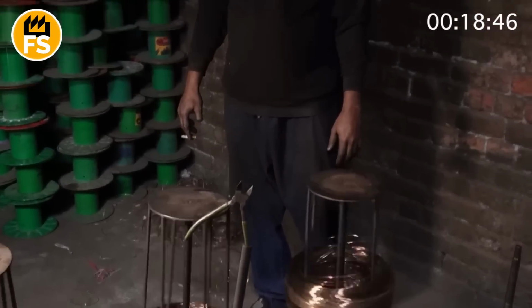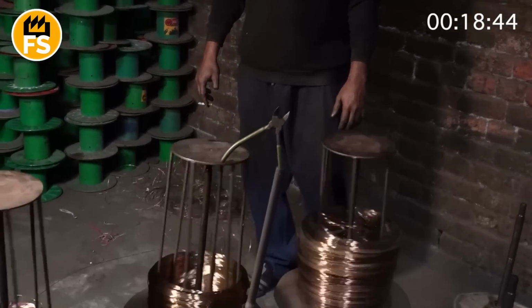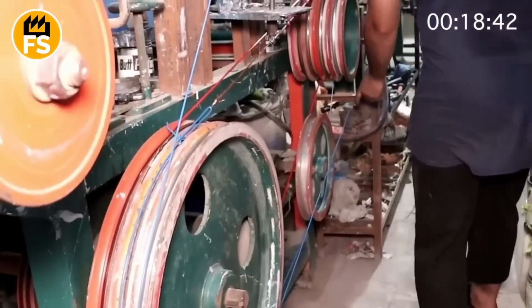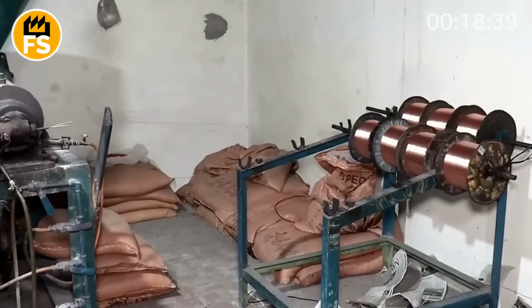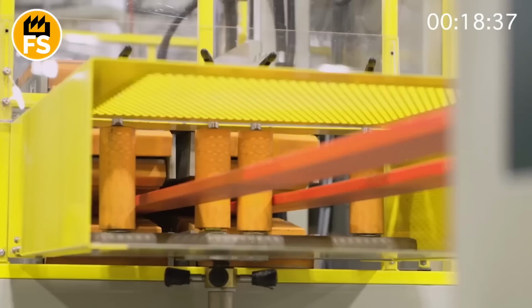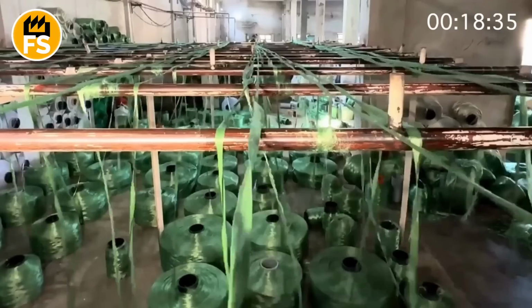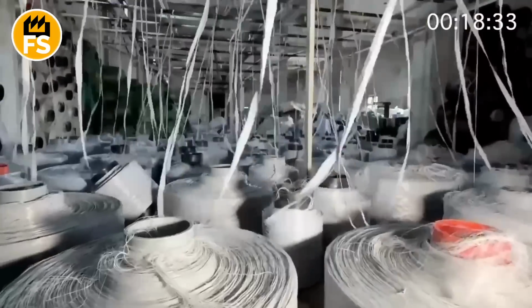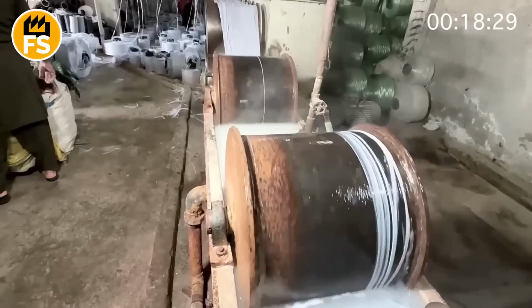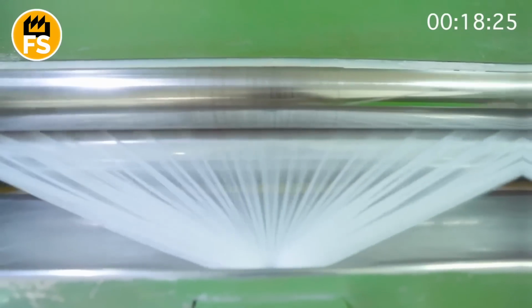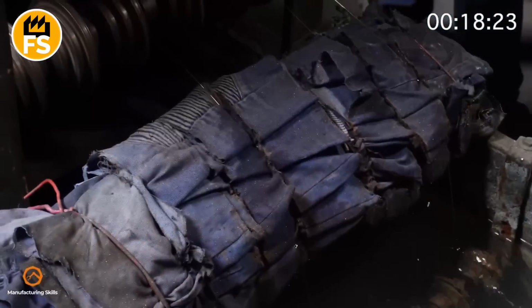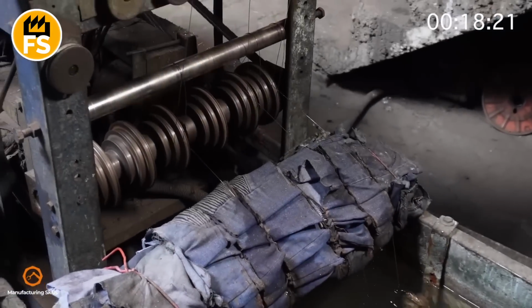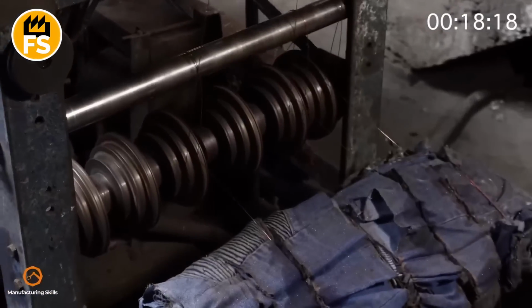On average, up to 6 miles of cable are wound onto one spool. That's almost 32,000 feet of heavy, multi-insulated wire that, under voltage, can carry hundreds of thousands of volts. An error of just half an inch in the spool's diameter, and the cable might start coiling incorrectly, shifting, compressing, overheating. In the worst case, it gets damaged even before installation. And that's tens of thousands of dollars in losses before even starting.